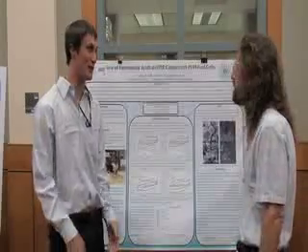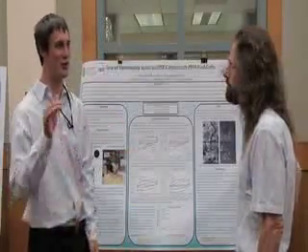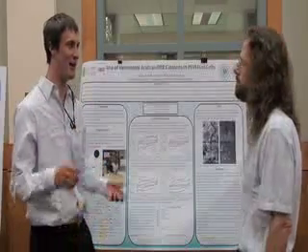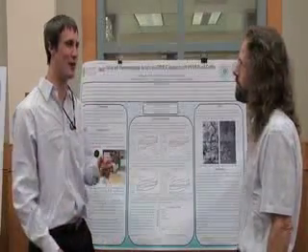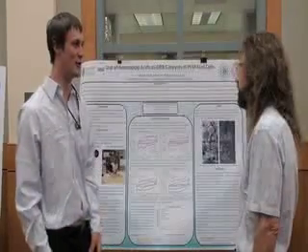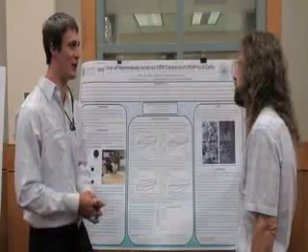So in a hydrogen fuel cell, we have hydrogen coming in, it splits. The protons go through the membrane, electrons go around to make an electric current, and then they come back together on the cathode to make water with oxygen. And so the catalyst right now used on the oxidation reduction reaction is platinum and platinum alloys, and those are really expensive and they're not fully efficient.